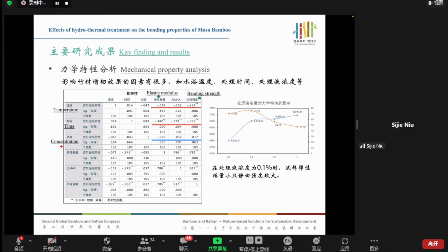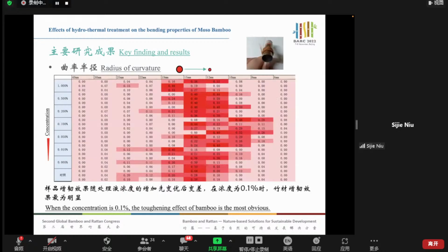That's partially due to the mechanical nature of the bamboo has no linear relationship versus flexibility of the bamboo. Only at the concentration of 0.1 of the treatment solution, the specimens have small modulus of elasticity. This slide shows the radius of curvature. The darker the color is, you can see the higher percentage of the bamboo materials are. And the conclusion is when the concentration is 0.1 percentage, the toughening effect of bamboo is the most obvious. It explains why the toughness and the concentration level have no linear relationship.